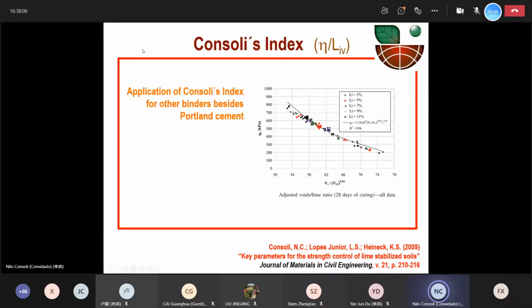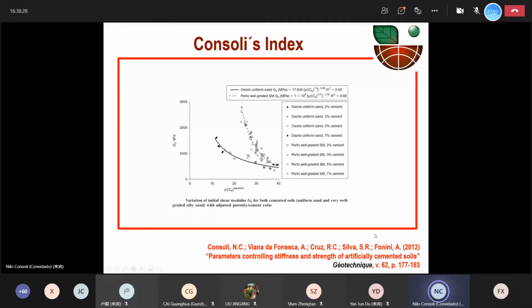Using now lime as the binder, for example, we published in 2009 the idea that by varying the porosity and the volumetric amount of lime, as with cement, you can also get unique curves for strength. Here, it was a paper from 2012 at Géotechnique, proving that besides unconfined compressive strength and splitting tensile strength, we can also control the initial shear modulus of the material based on this same index. So not just strength, tensile or compressive, but also the initial shear stiffness is controlled by the same index.